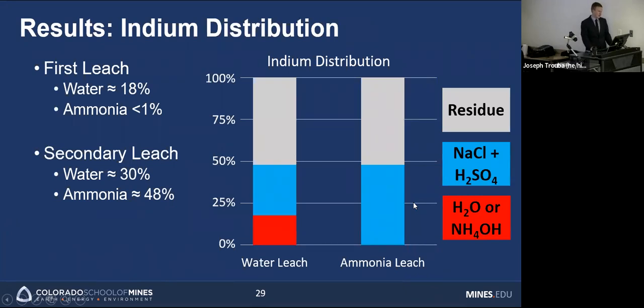But to get back to critical elements, in the first stage water leach, 18% of indium reported to the leachate, whereas in ammoniacal leaching, none of the indium was leached with ammonia. In the second stage, 30% of the indium combined leached during the sodium chloride sulfuric acid step, whereas for ammonia, 48% was recovered. If you notice, 30 plus 18 is 48%. This means that indium that was leached during the first stage of water leach, but not ammonia, all reported to that same leachate, and both resulted in relatively similar residues.